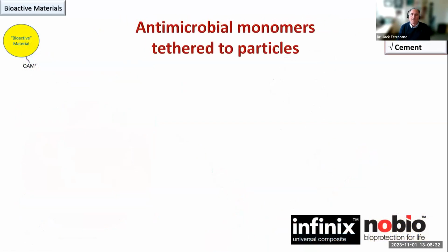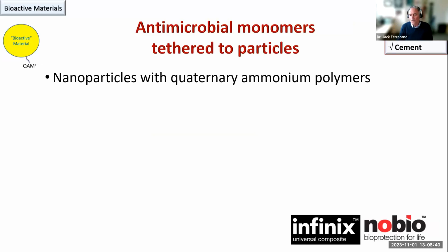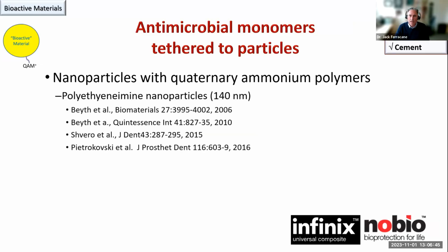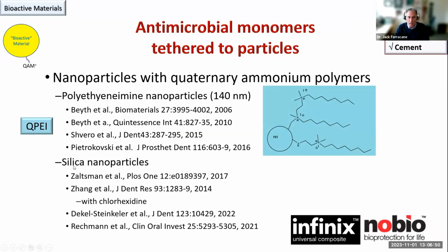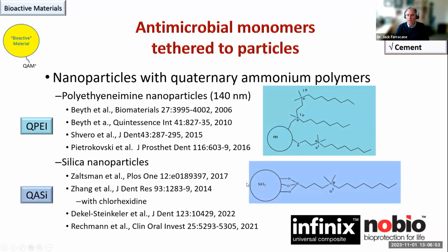So we see a variety of different antimicrobial monomers that have been tethered to particles and then put into commercial materials. And an example is the Infinix product from Nobio. So these are nanoparticles either made with polyethylene imine or silica nanoparticles. And basically what it is, a quaternary ammonium that's attached to the particle. So again, it's going to stay within the resin. It's not released, but it could cause bacteria to either not stick to the surface or to be killed when it attaches to the surface.